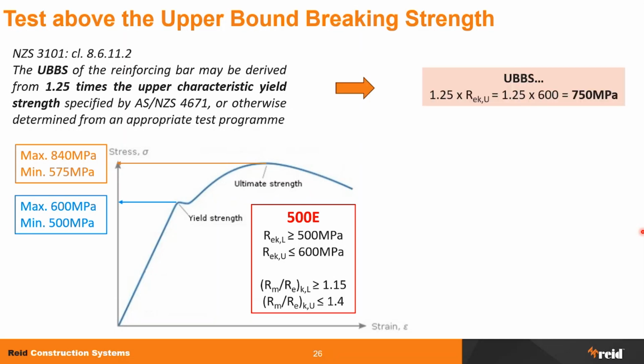But then we look at the definition of the upper bound breaking strength from 3101. So if we don't have an appropriate study conducted on these bars, we can consider as upper bound breaking strength 1.25 times the upper characteristic yield strength, which is 600 for a 500E grade. Therefore, we have 750 megapascal. And so then if we look at what is actually produced by Pacific Steel, for example, we can see that the upper characteristic ultimate strength never goes beyond 725 megapascal.